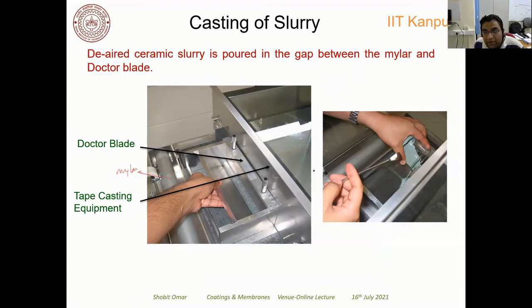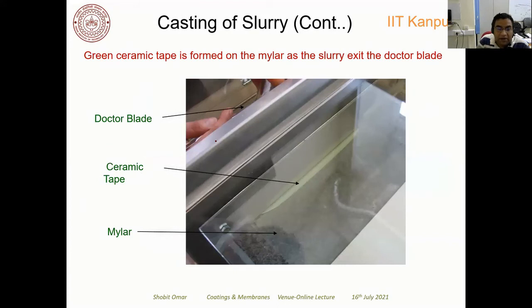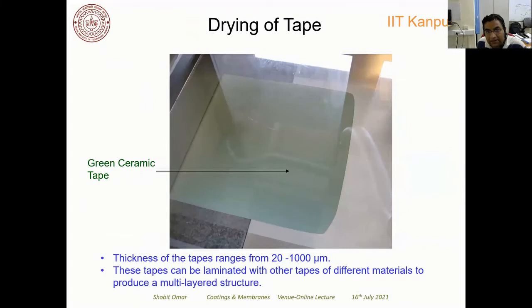And basically you pour your fluid here, and this gap that you see will control the thickness of the tape that you will get. After the de-airing of the slurry, you pour the slurry in this space, and because of the movement of the mylar, you will get a green ceramic tape coming out after you pour all the ceramic slurry in that particular space present in the doctor blade. This mylar continues to move at slow speed, and finally you will get a green ceramic tape. You can get tapes of 20 to 1000 micron, which are basically thick, right? And these are not thin films; these are thick tapes.